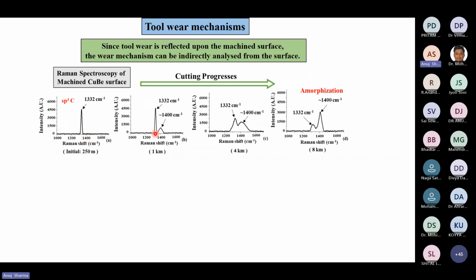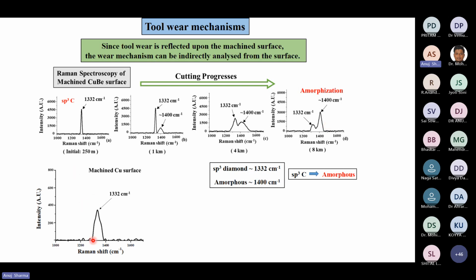So it means that amorphization, the amorphous atoms, were increasing, which is shown by this peak at 1400 centimeter inverse. This keeps on increasing, which means the amorphous atoms are getting more and more on the workpiece surface. Whereas in the case of the copper surface, there was a single larger peak which corresponds to diamond only. So there was amorphization taking place in the case of copper beryllium, but in the case of copper, there was only atom by atom wear of diamond taking place.